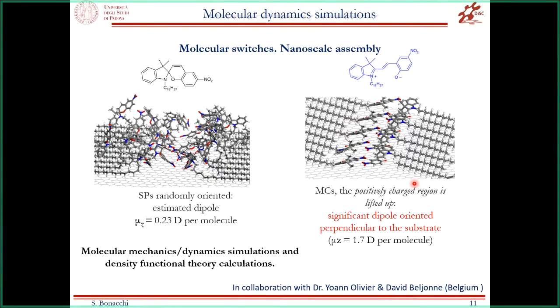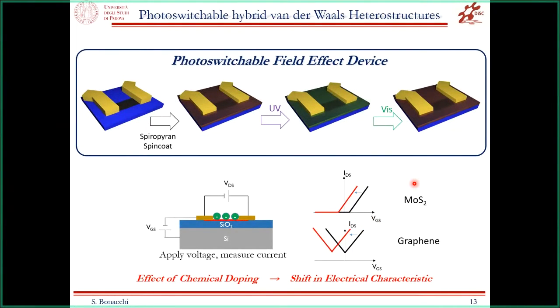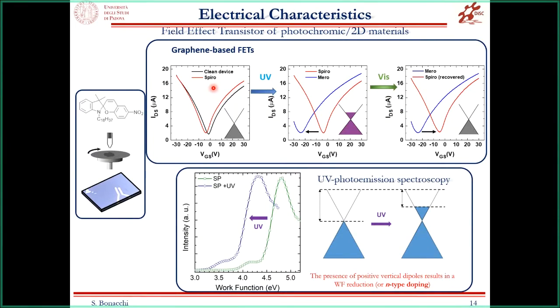So to prove if this kind of approach, the possibility to use molecules as building blocks to create a photoswitchable lattice on top of a 2D material, can actually induce an electrical modification of the graphene, we perform field effect transistor analysis. In particular, for people who are not in this field, basically we apply a voltage and we measure the current across the film. And what we observe is that as soon as we spin coat our spiropyran molecule on top of graphene, there is not really an effect on the Dirac point of graphene. That means that the moiety, even if it is able to form a high-order lattice assembly on top of graphene, is not able to induce any effect on the electrical properties of the graphene below.